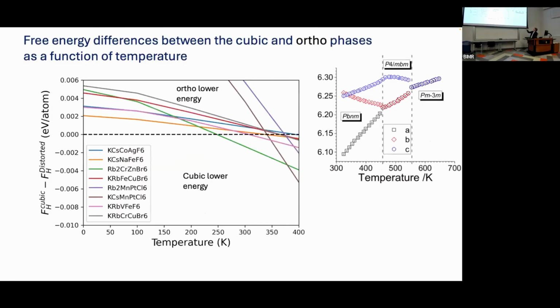So we can start to approach this problem by mapping out the phase diagrams. In this case, we take this one potential that's been fine-tuned, and we calculate the free energy difference between the two phases as a function of temperature. So it's a very expensive calculation that becomes easy to do because of the cheap potential. And we can calculate the temperature at which the cubic phase becomes lower in energy for these different compositions. And so now we have a database of stable materials that are also entropically stable, potentially at higher temperatures.